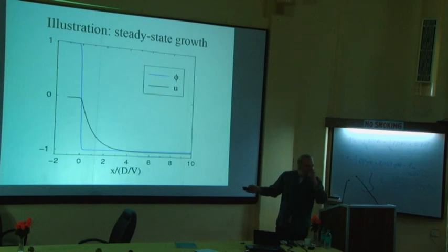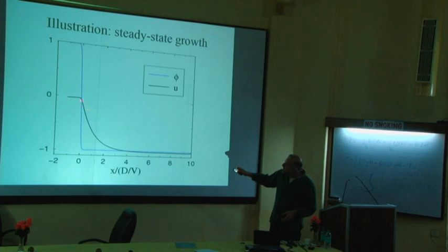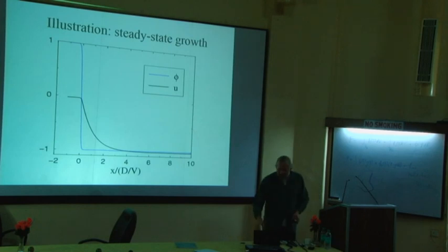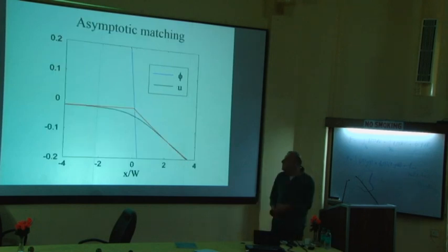That's my outer solution that I can calculate. So I fit this straight line and exponential to some part of the solution that is close to the interface, but outside of the interface. And if I plot these asymptotes, those are the two red lines. And you see, if I prolong these asymptotes to the interface position, here 0, I get some value. And this is the boundary condition that the outer field sees.